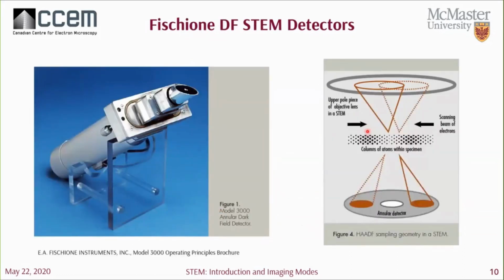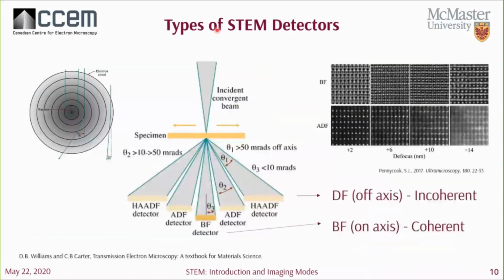So here I just want to put some rectangle drawings of our ADF detectors into perspective. This is the donut-shaped detector itself, and it's constructed so that the outer detection angle is about 6 times larger than the inner collection angle. It's a scintillator made of yttrium aluminum perovskite crystal, and it produces a photon when it's hit with an electron. These photons travel through the quartz cylinder attached to a photomultiplier tube separated by an aluminum shield. An application of the signal from the photomultiplier tube is described by a range of grayscales, giving us our grayscale image, as we see here, just grayscale.